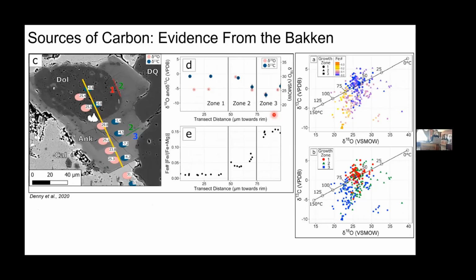But there are a lot of similarities between what is observed in the Sappington and what's observed in the Bakken. This is a paper that was published recently in the Bakken, and this is a BSE image, so backscatter electron, but it tells us something very similar to the EDS maps. They see very similar morphologies of dolomite in the Bakken as we do in the Sappington. Just like I showed you in the Sappington earlier, there is a magnesium-rich core here in this dark color, surrounded by varying degrees of iron-rich rims. In this case, they've got 2 and 3 different rims identified in the Bakken.